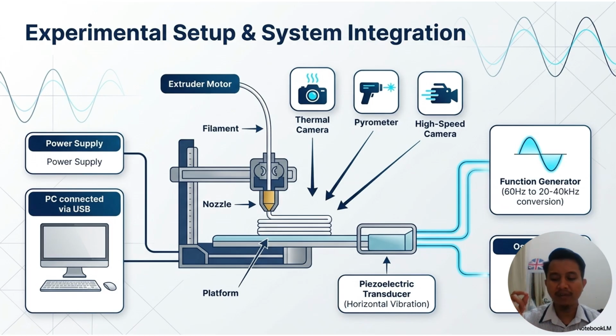This transducer is driven by a function generator, capable of converting a standard 60 Hz electrical input to a high-frequency signal in the 20 to 40 kHz range. An oscilloscope monitors the signal in real time to ensure frequency and amplitude stability throughout each experiment. Critically, we have 3 measurement instruments observing the sample during actuation: a thermal camera to map the localized temperature distribution on the SMP surface, a pyrometer for point temperature measurement, and a high-speed camera to capture the kinematic dynamics of